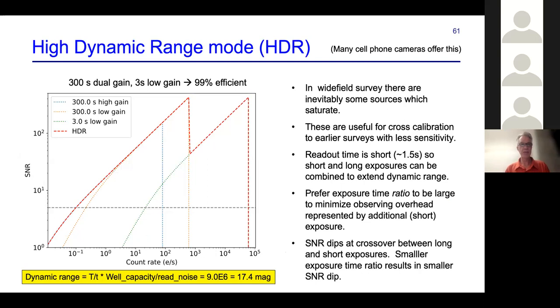Now, because we have 100% duty cycle and fast readout time, we can do another trick, which you also have in your cell phone. It's called HDR mode in your cell phone, for high dynamic range. What you do is you pair a very short exposure with a long exposure. And the short exposure is effectively duplicate imaging time, and so there's a loss of efficiency. So you'd like about a 100-to-1 ratio in exposure times so that you're about 99% efficient. And what you do is you pick the value from either the short or the long exposure according to how bright the signal is. This can extend your dynamic range by a factor of 100.